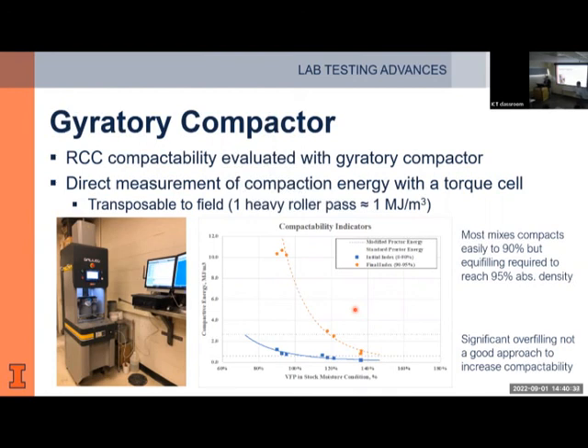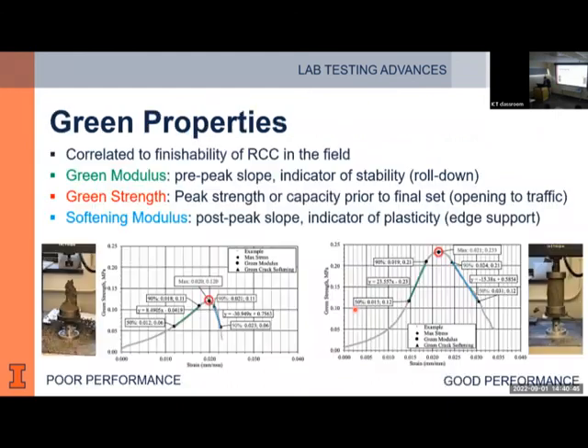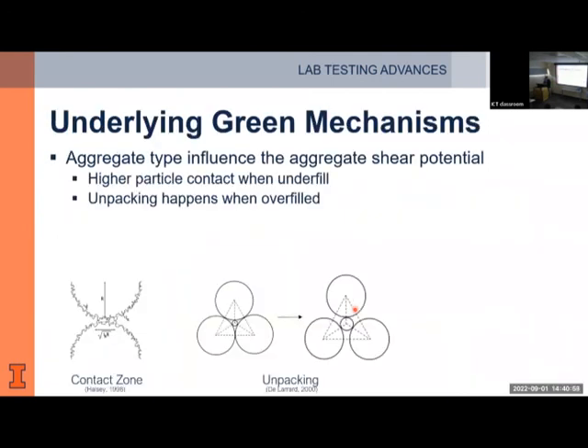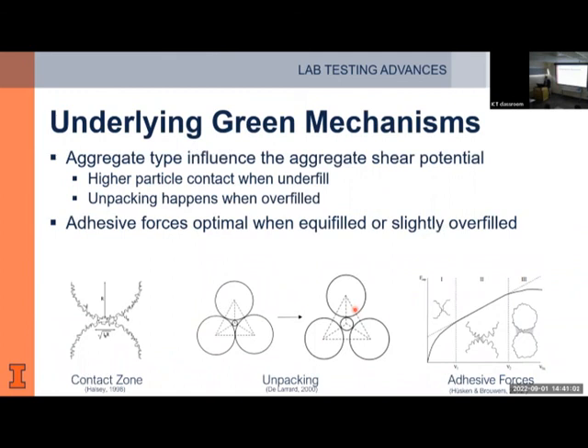Follow-up question on slide 24: The concrete was tested within 30 minutes — and in the next slide, there's a contact zone and shear stress holding the pavement together. Is there a reaction happening in the first 30 minutes? Jordan: Definitely — it's like building a sandcastle on the beach. When you add water to sand, you get capillary surface tension forces. These are the adhesive forces at play — not a hardening force from cement paste hydration, but a hydraulic phenomenon of capillary and surface tension.